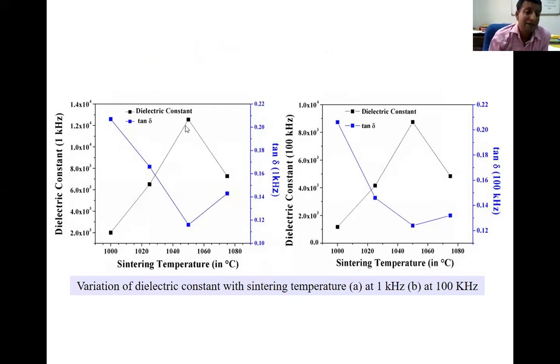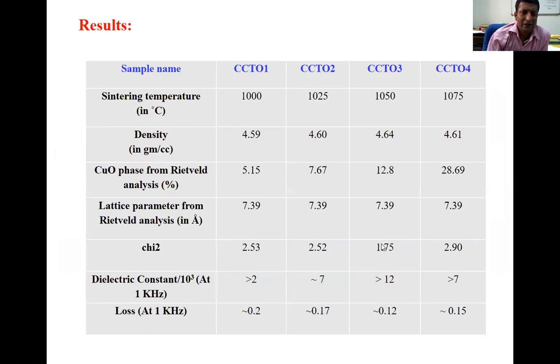We optimized the sintering temperature at 1050 degrees Celsius. We are getting the better dielectric property. The dielectric constant is also high, and of course the dielectric loss becomes less. So we optimized this sintering temperature, and the time, of course, is half an hour, and that was the same. And so this is the whole summary of this particular compound, where the temperature variation was 25 degrees.